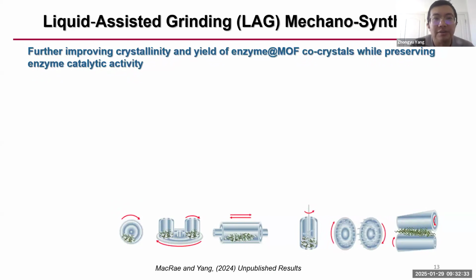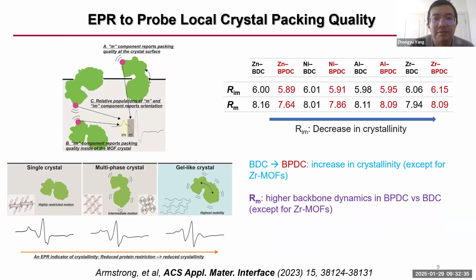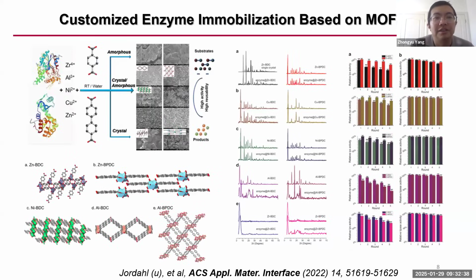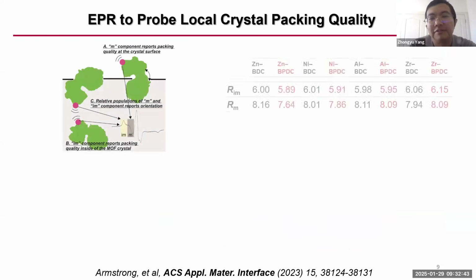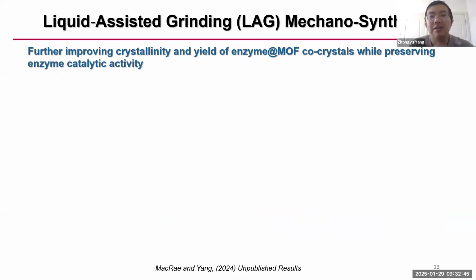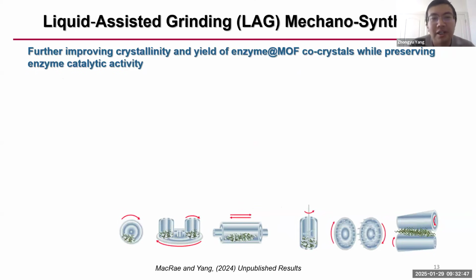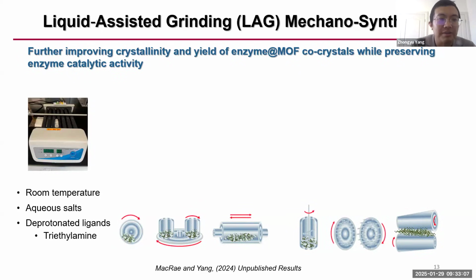We, of course, are not so happy with the quality. That's because, let me go back, all of these MOFs are made in water phase. And you know, when crystals are formed in water phase as compared to organic phase, you have low crystallization and low yield. So we introduce the liquid-assisted grinding method. So basically, you have a tube and stainless steel beads, and then you rotate the tube so the beads are enhancing the interaction between the enzyme and the liquid, right? And the setup is quite simple.